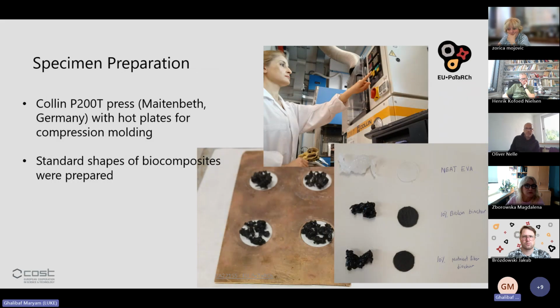The next step after making the biocomposite, which you can see in one of these pictures, one with the pure polymer and the other 2 black ones including the biochar, was that I had to do the specimen preparation from the biocomposite into the standard shape. Here it's this circular shape, made through thermocompression molding for the rheological testing. The molding was also performed under controlled conditions to ensure uniformity and consistency across all the samples, and all conditions were set the same as for that blender.